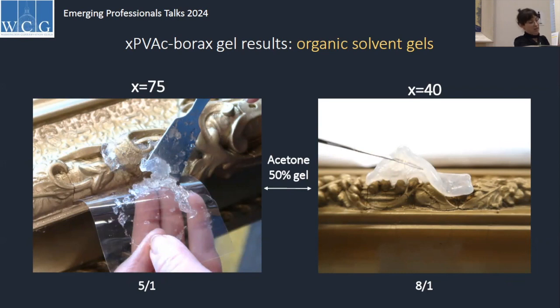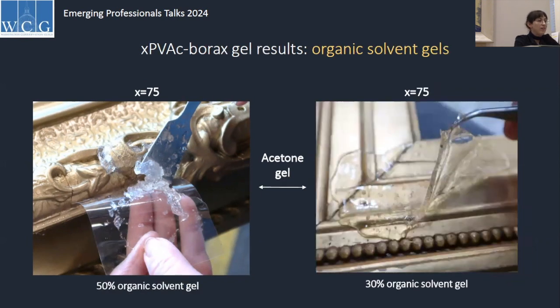Next slide, please. Having said that, if you reduce the solvent content in the system, you get a vastly different result. So you can see this is the same polymer with 50% organic solvent versus 30% organic solvent, and already the morphology is different. So if you're wanting a gel that's got more water in there with a little bit of organic solvent, then this polymer would be suitable. Next slide, please.